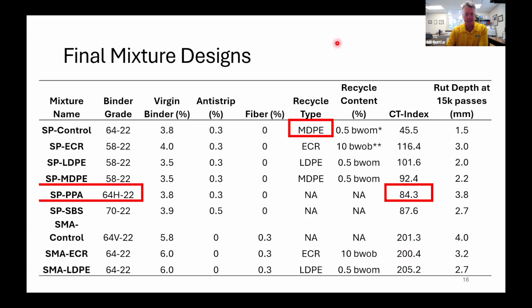So more details about the mixes. We swapped the order of the mixes because we were able to hit the elevated 80 minimum CT index with one of the modified mixes. So we moved that down in the list, and then the control mix was made with plastic. So we got another plastic mix out of that, and you can see the anti-strip and fiber dosages. Somebody had asked in the chat a second ago, how much plastic do you put in? We generally target, all things being equal, about 0.5% plastic by weight of the mix. So for every 5% asphalt content, if you put 0.5% plastic, it's about 10% plastic by weight of the binder. But by weight of the mix, it's about 0.5%.